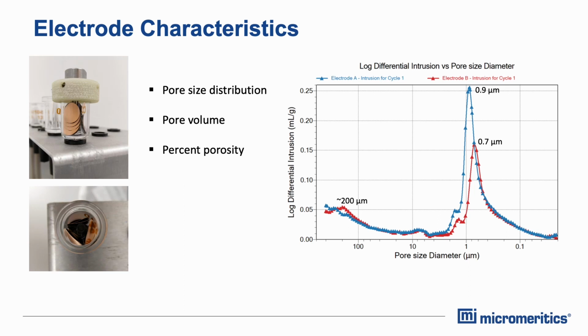And we also see from the higher peak for electrode A that this comes with a higher volume at this pore size. As I already mentioned, pore size distribution as well as pore volume and also percent porosity are the parameters that we can get from mercury intrusion measurements. I show you two pictures on this slide also from the preparation of this sample. The electrode was punched into circles, and those circles were put into the penetrometer, which is the kind of sample tube for this measurement. And you see, in order to fit the decent amount that we need for the measurement into this bulb of the penetrometer, the circles many times lay quite close to each other.